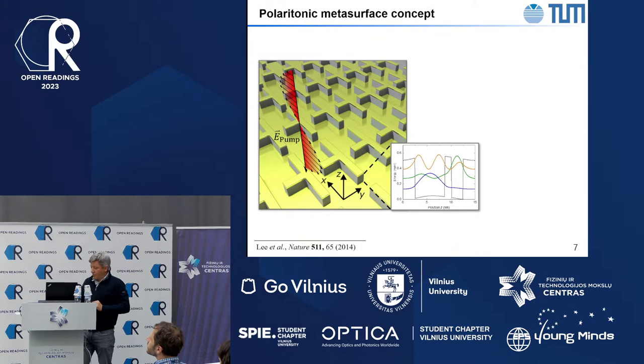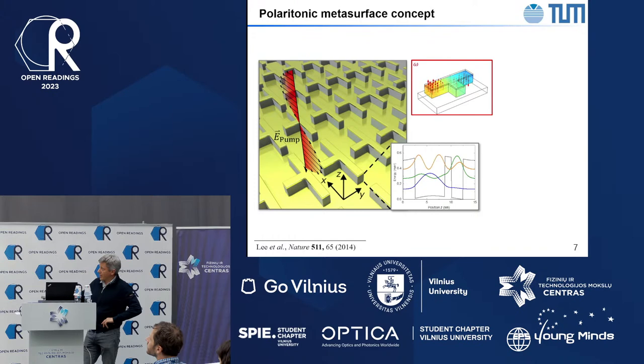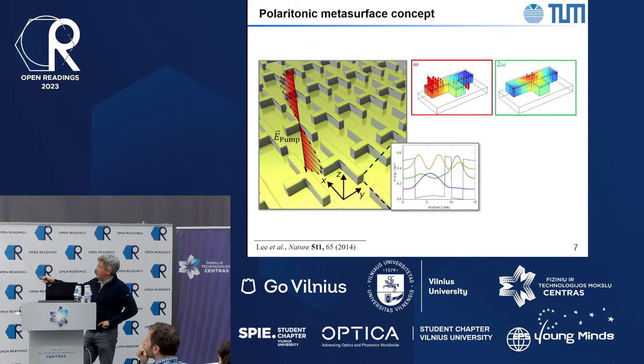Then you have an input at frequency omega, and this input polarization couples to antenna resonance in this direction. So current starts running inside of this antenna, a physical current, it's a metal antenna, and this current produces an oscillating electric field in the material. Now it oscillates up and down. This is the electric field at frequency omega, and you have strong nonlinear response. So this oscillating electric field produces oscillating polarization that has some component at second harmonic generation, given by the square of this electric field times the nonlinear susceptibility. Now this oscillating second harmonic polarization can excite another antenna resonance from within, and that means the current is going to be flowing in this antenna roughly in this direction, at least that's how these T-shaped antennas are designed, and then this antenna will re-radiate the second harmonic generation into free space. So that's how it's happening.